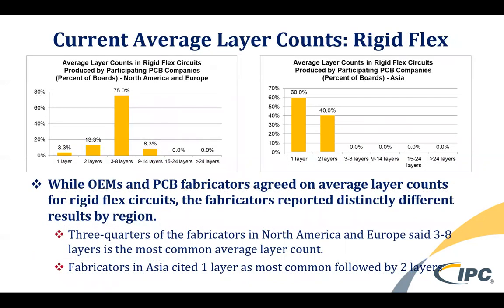Also looking at the rigid flex, if we take a look at the participating companies, the ones that did participate in the sample in terms of rigid flex, which again is a major enabler for military and aerospace, you see a large sweet spot between the 3 and 8-layer counts. A lot of those are 6 to 8 layers for this type of technology. In Asia, you don't typically see much, at least on the rigid flex side, again, in the sample that was provided, you don't see much change going beyond 2 layers in terms of rigid flex. But I'm sure there are some in the 3 to 8-layer range, but very small compared to North America and Europe. And again, that's driven by the end-use technology.